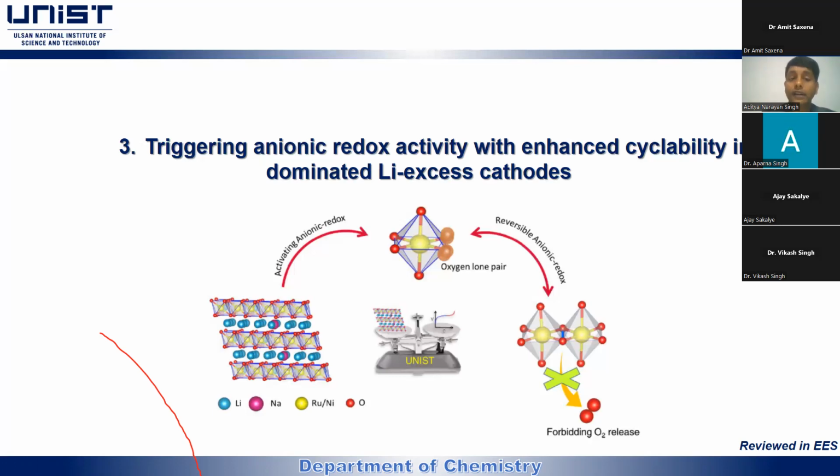As I explained before, our lithium ruthenium oxide does have anionic redox, that is, oxygen participation. That's the reason they have high capacity. But when oxygen comes into the picture, since it is a gas, it has a high propensity to leave the crystal structure, so it makes the crystal structure fade. So a compromise, a trade-off, has to be made: still use anionic redox, but make it sustain. That is our next goal. It has to be reversible for a long time.